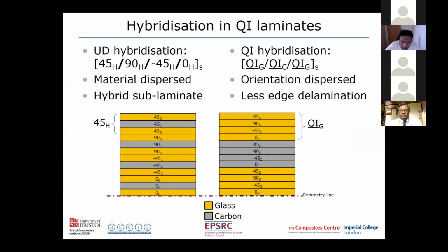We can make these into quasi-isotropic laminates, and there are two ways that we can make a hybrid. We can do it by dispersing the material. In this case, we've got a hybrid sublaminate of 45 glass, 45 carbon, and 45 glass. And that 45 hybrid sublaminate is then repeated with different orientations through the thickness. So that's a material dispersed laminate, or we can do it this way, where we disperse the orientations but keep the materials together. So we have a quasi-isotropic glass, and then a quasi-isotropic carbon, and then a quasi-isotropic glass.